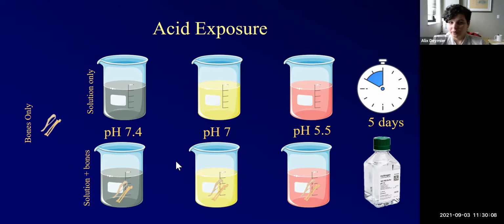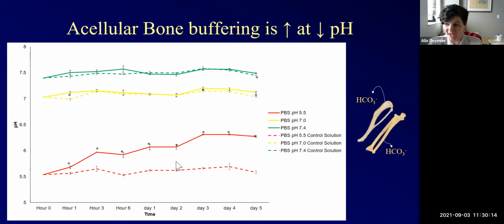So first we wanted to know, if I just put a bone in a solution, will it buffer? Does it have that ability to actually buffer the pH? What you can see is that the answer is yes. So here's pH, and down here is the time. So we ran up to 5 days, but we took pH at multiple time points. And you can see at low pH shown in red, here's my control group. So this had no bones in it. Now the pH essentially stays at 5.5. But if I have bones, man, they are so good at buffering. I was able to raise the pH by almost a full pH value.